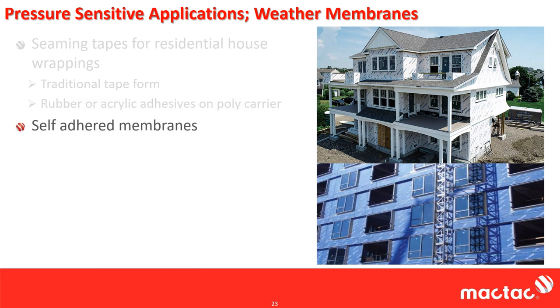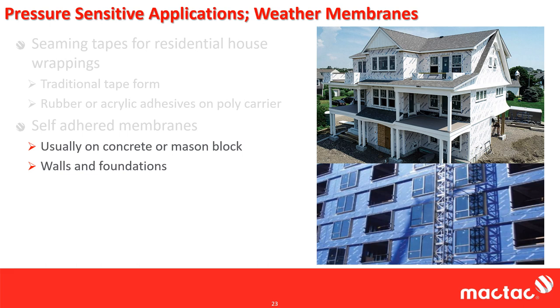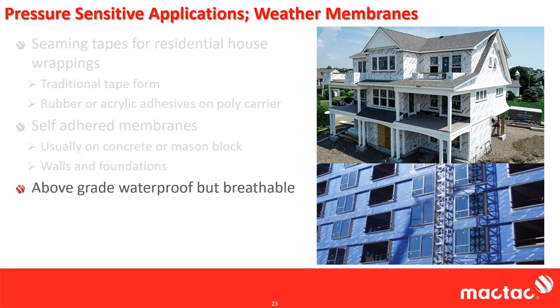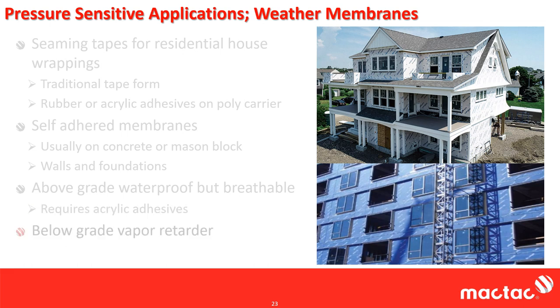Then there's self-adhered membranes, which are actually PSA-coated. These are used where mechanical fasteners aren't possible, such as mason block or concrete, usually found on walls or foundations. Above-grade membranes are a lot like Gore-Tex, and they keep the liquid water out but allow water vapor to pass through or breathe. These adhesives must be acrylic. This is a function of acrylic adhesives. Rubber-based adhesives repel water, but acrylics will allow for water vapor to pass through while keeping bulk liquid water out.